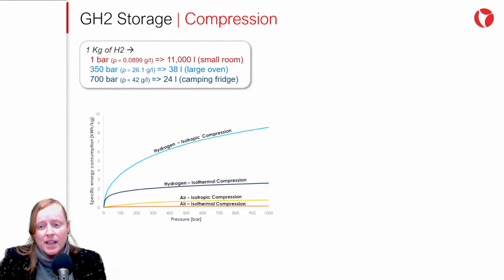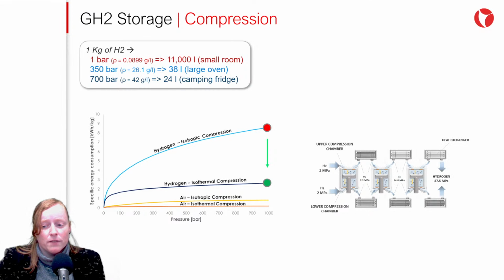For example, hydrogen compression up to 1,000 bar requires 2.6 kilowatt hours per kilogram for ideal isothermal compression and 8.6 kilowatt hours per kilogram for isentropic compression. The mechanism to bring the upper curve closer to the lower one is to carry out a multi-stage compression with intermediate cooling. This brings the process to an intermediate thermodynamic point, although with greater mechanical losses.